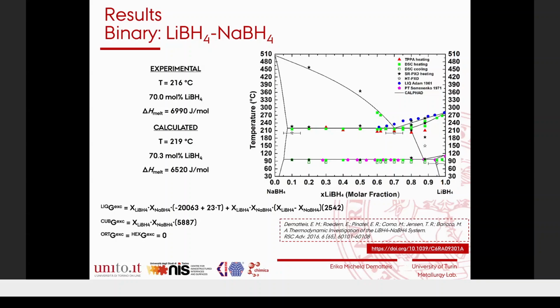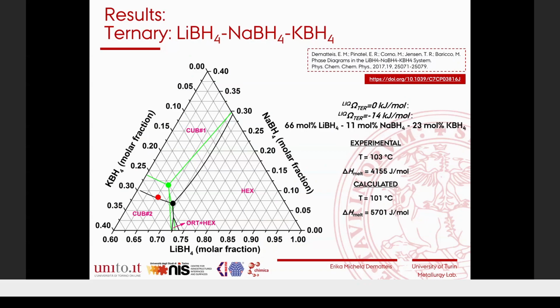So as you can see in the slide, we were able to describe with a parametric description, so defining interaction parameter and defining the Gibbs free energy in all temperature and composition range. Once we described the binary lithium sodium, we moved and we also performed an optimization of the other binary systems, so sodium potassium and lithium potassium. And then we were able to extrapolate and use our thermodynamic database to calculate also phase stabilities in the ternary